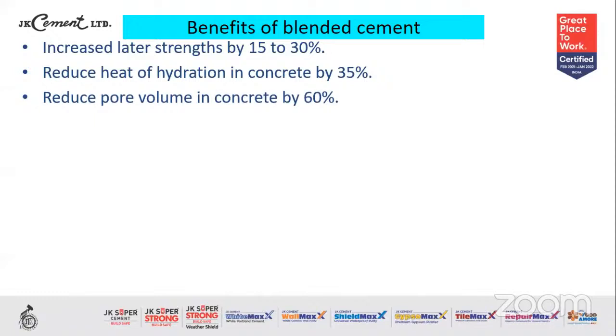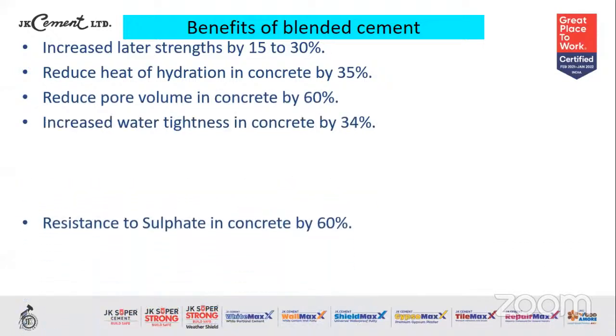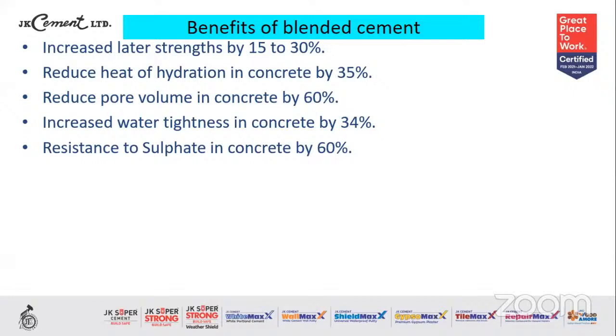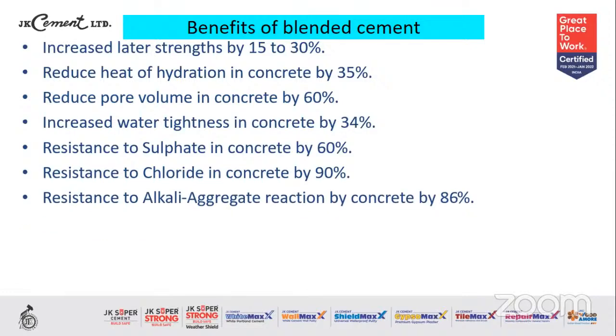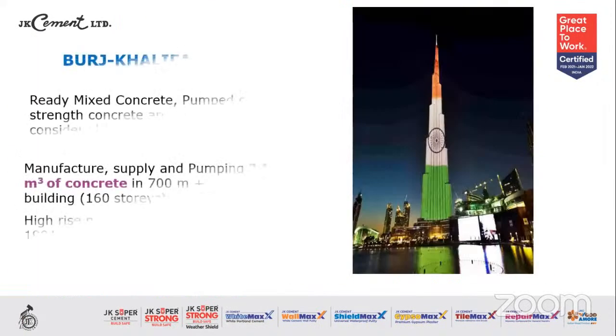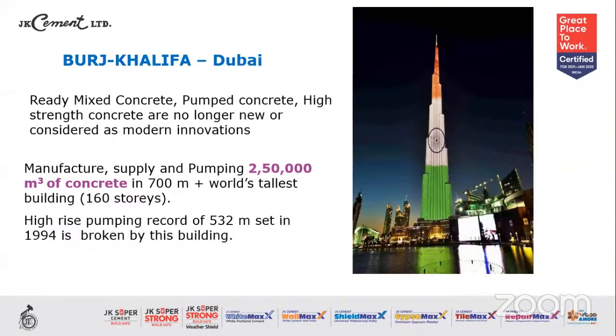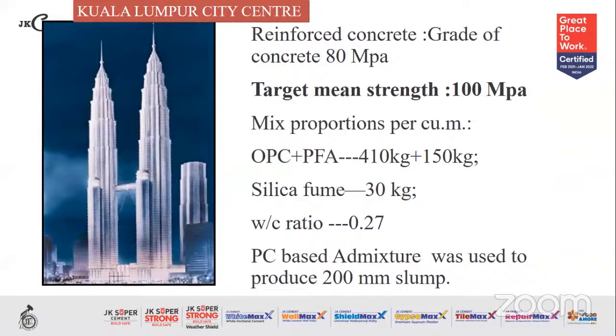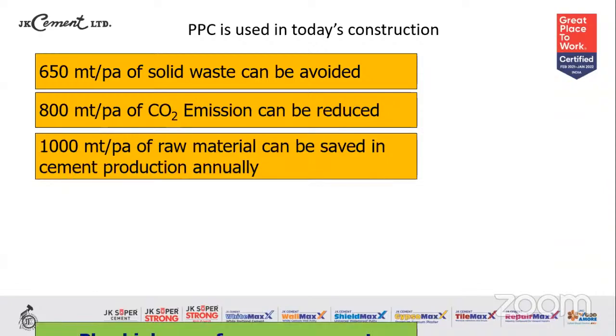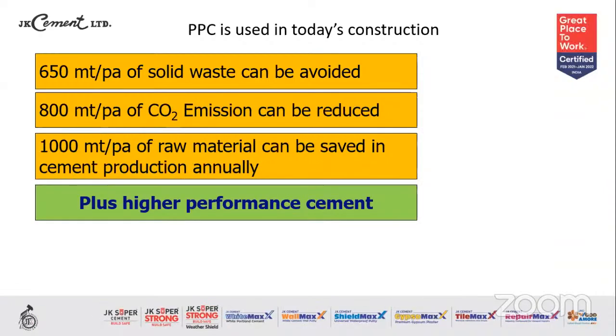There are all such technical benefits which you can envision. In all possible ways, blended cements are far better in terms of increased strength, reduction of heat, reducing the pore volume in concrete, increasing the water tightness, and resistance to aggressive sulfates and chlorides, etc. So overall, we can get a durable product. And no doubt, blended cement can be used to construct buildings and structures of international repute, like the Burj Khalifa, or for that matter, the Twin Towers in Kuala Lumpur. The concrete used blended cement entirely. So no one should have even an iota of doubt on that. The same blended cement is going to contribute a significant reduction in carbon dioxide emission.